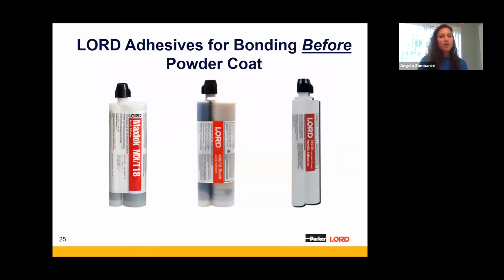Now, the adhesive that we recommend for bonding before powder coat are these 3 options. We have the Maxlok, the 400 series, and the 810, which we featured in the earlier slides. They all have temperature resistance of 400 degrees Fahrenheit or 204 Celsius up to 90 minutes. So you don't have to worry about the bond line degrading as it goes through the oven. Another great advantage of LORD Acrylics is they will come out even stronger out of the oven than they would be just curing at room temperature. And this is a unique property of our technology.